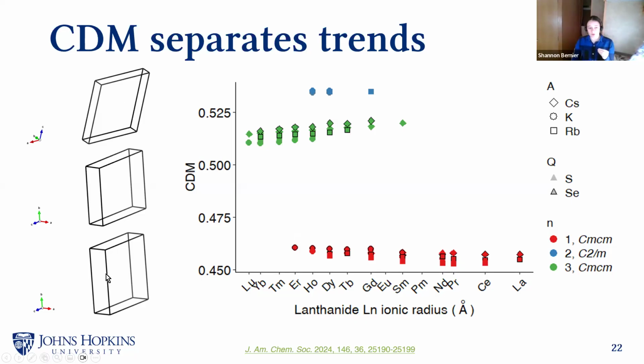And the reason for this comes when you look at their unit cell shapes. The n=1 and 3 are both orthorhombic, but the n=1 is kind of narrow in this one direction, in the C direction. It's much more narrow compared to the n=3 structure, which has a more widened c-axis. And then when you move to the n=2 structure, you have that same width of the c-axis, but now you have a little bit of a cant in the angle here. It's no longer 90 degrees.